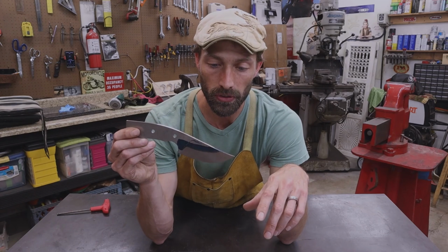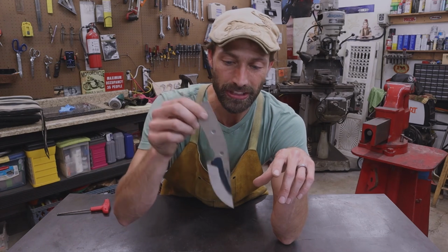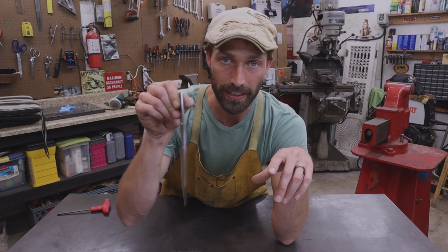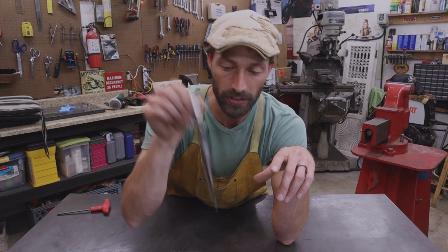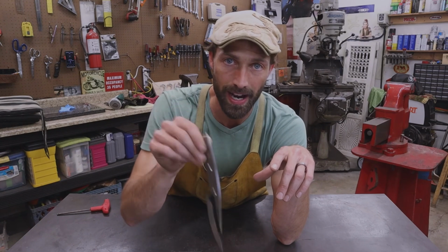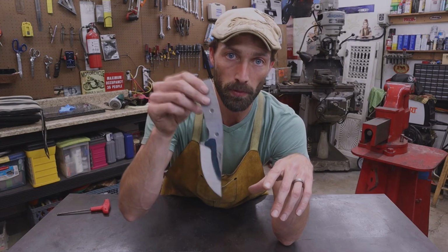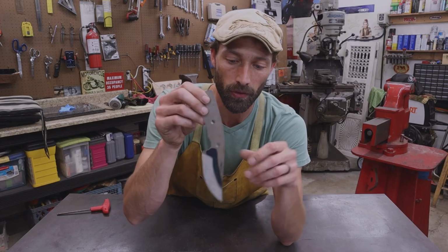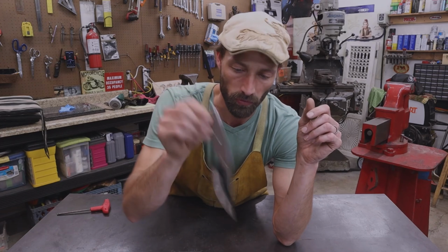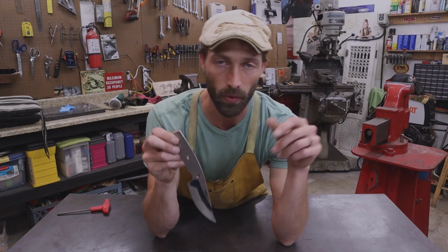And then when we go to quench it, we're going to agitate the knife, not sideways because that could introduce warps. We're going to agitate it really fast up and down to try to release the vapor barrier that's forming on the metal from the heat. So we're just going to really quickly agitate it in the oil.